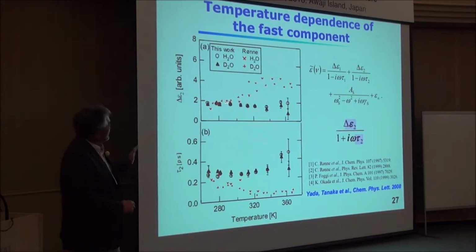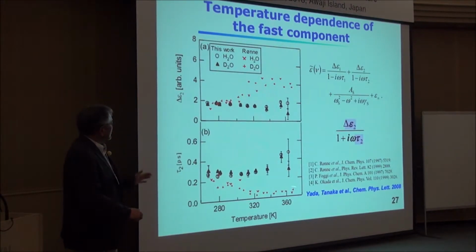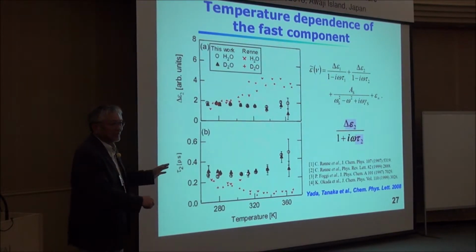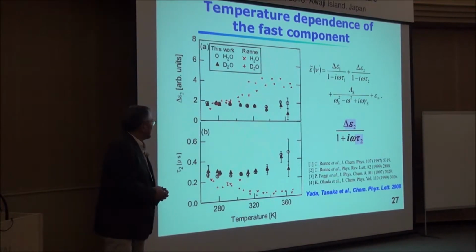And you can see the amplitude doesn't change so much with temperature. And also the time constant is around 300 femtoseconds, and also not much changed. This is the signature of the second Debye.